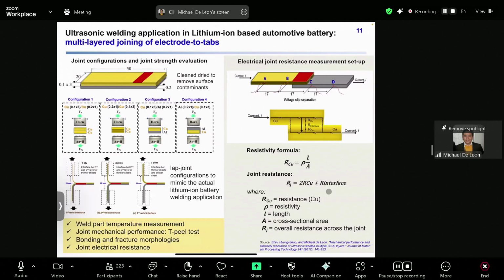Interestingly, when we compared UW to solder joints, we found that UW actually performs better despite not using any filler material. The solder itself, like indium tin, adds resistance at the interface, something UW avoids entirely.